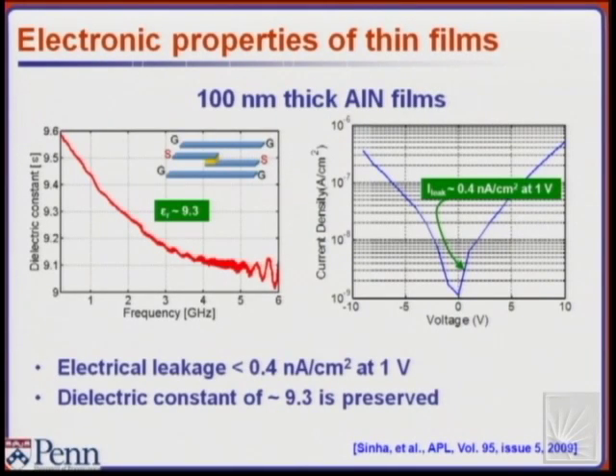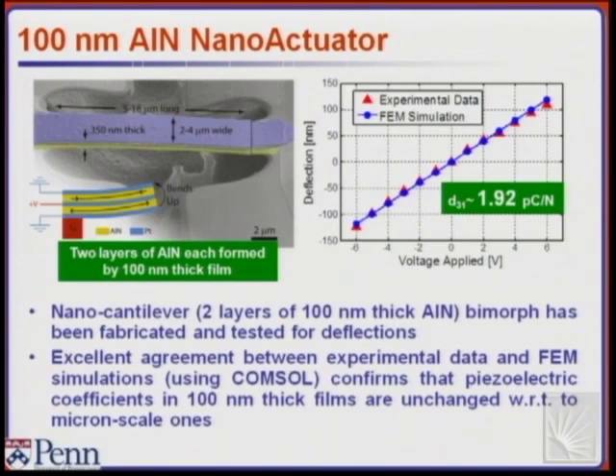It shows that it's low leakage, and therefore will probably be good for making those mechanical elements and reducing the off-state leakage as well. But we went ahead and made a nano actuator. It's basically half of a switch, which is your mechanical actuator. It's a bimorph. We stacked two 100 nanometer thick aluminum nitride layers on top of each other, sandwiched between platinum electrodes that were 50 nanometers each.